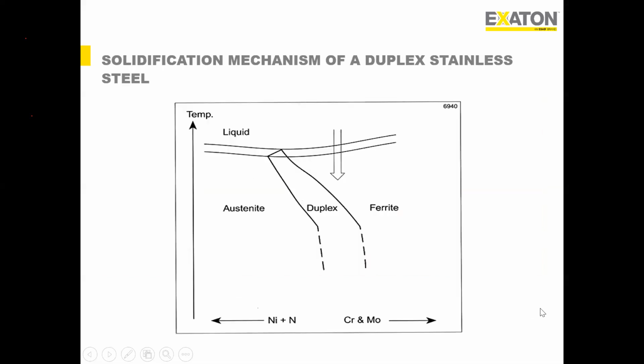Okay, so this is the solidification mechanism of duplex stainless steel. Specifically, let me explain, it is applicable for both base material as well as for the weld metal. So when you do the welding, it goes to the liquid phase, which is here. And the liquid weld metal slowly cools down over a time period. So what happens when it gets solidified? The first phase which forms is basically ferrite or delta ferrite. And slowly over the time period, the delta ferrite transforms into austenite. And that's why it forms a duplex structure.